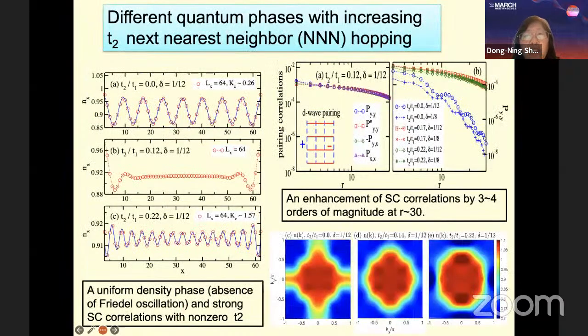Let's discuss the different quantum phases one by one. The first one is the CDW with very small T2 over T1, like T2 over T1 smaller than 0.1. We get this charge stripe phase. This is electron density as a function of x coordinates of the sample, showing this period. If we calculate how many electrons are inside each period of the stripe, there are approximately 4 electrons inside each stripe.